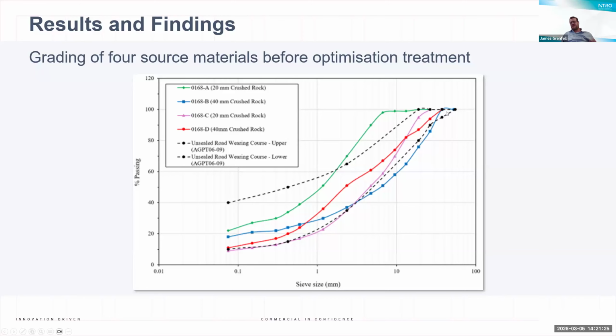sources. And this graph is now showing the gradations of those different crushed rocks plotted out with the requirements or advice for the gradings envelope also shown. So you can see that some of them, the green line seems to be quite on the fine side. The blue and the purple are quite coarse in certain areas, and only really the red one is sitting fairly close or closer to the middle of the grading envelope.